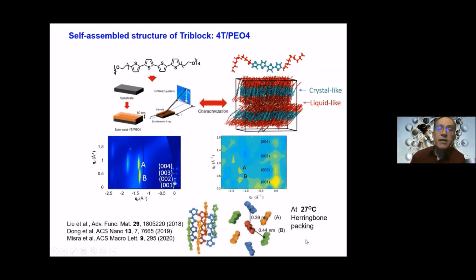Now this packing is how thiophene oligomers crystallize. So what this was telling us is that in our structure, these blue domains are sort of crystal-like, while these red domains, now we can also see they were liquid-like. Now this is a very interesting material because if you think about it, you have this perfect intercalation of these nanometer thick layers of liquid crystal that would defy classification as a solid or liquid.